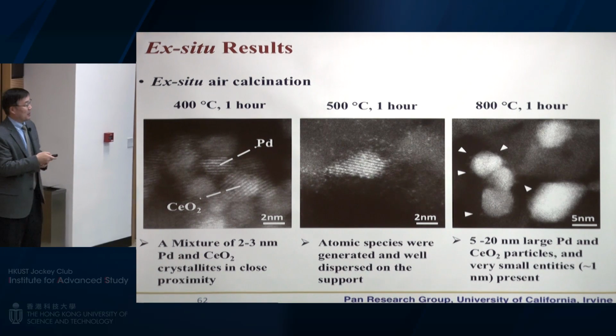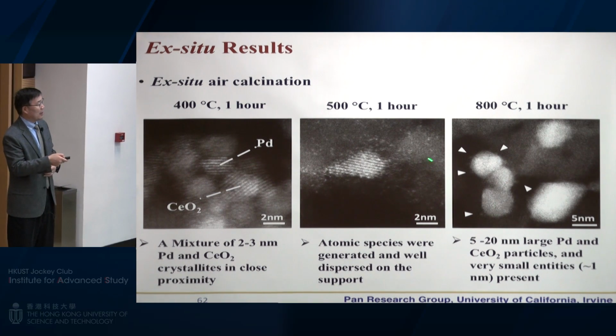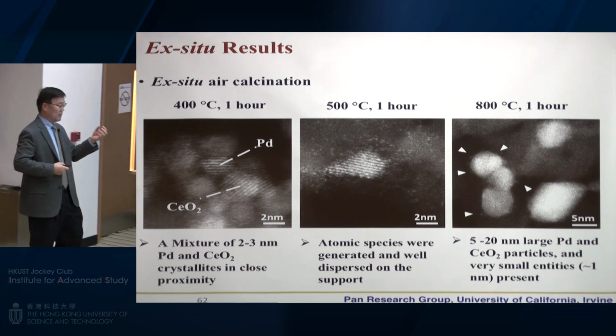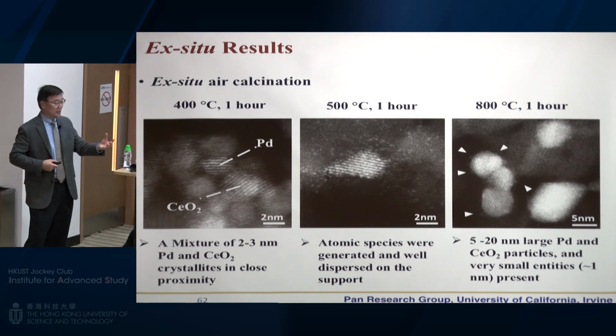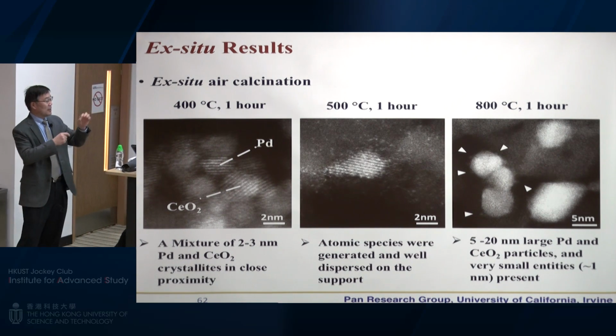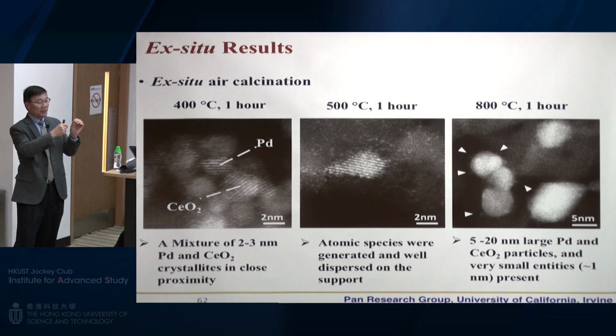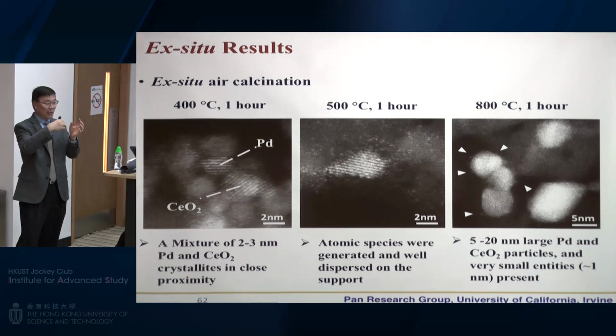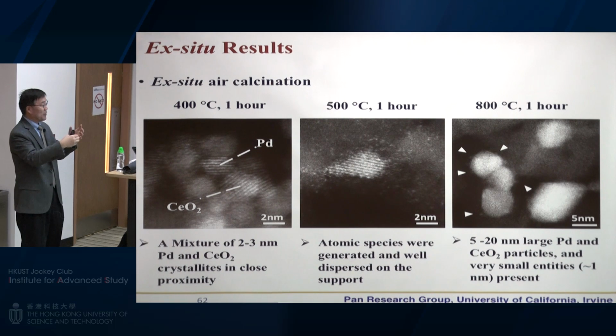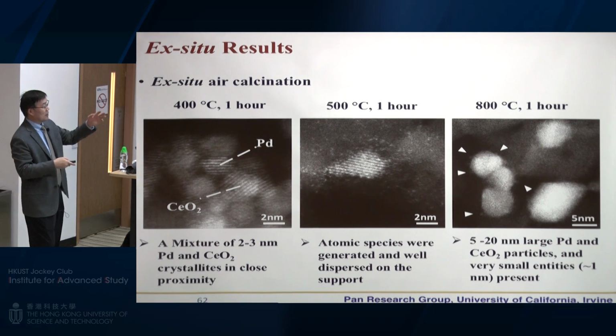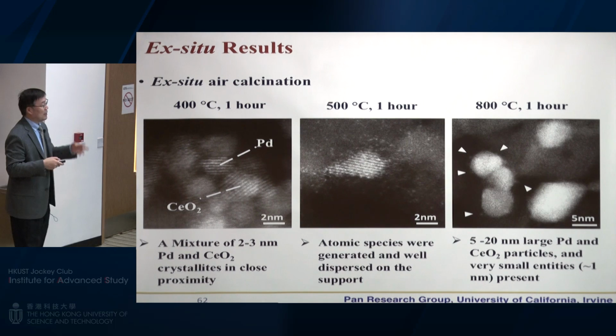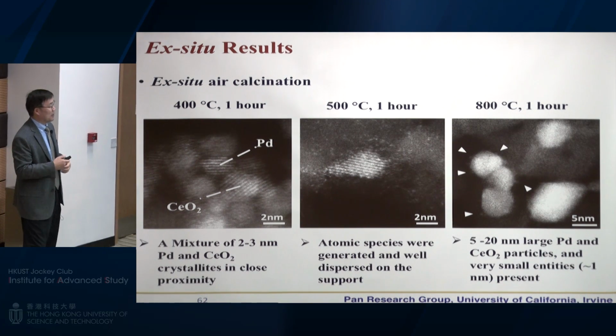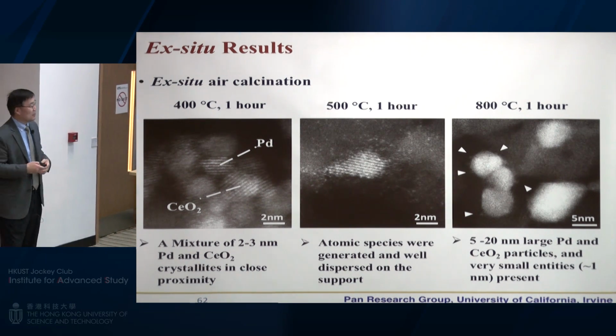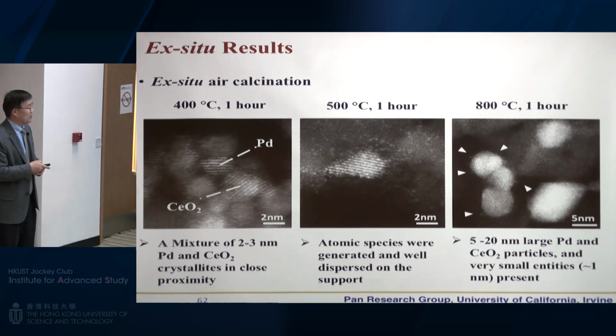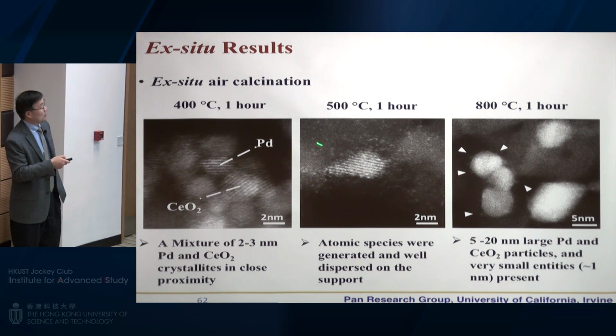I can tell you more about using this sample, and you see a lot of phenomena that are interesting for people like ceramists, metallurgists or chemists, because the atoms were leaving the particles at high temperature and atmospheric pressure. You see the atoms cluster and move around, the small particles disappear and large particles grow, like the typical sintering effect or Ostwald ripening, and a lot of things. I'll show you a few examples.